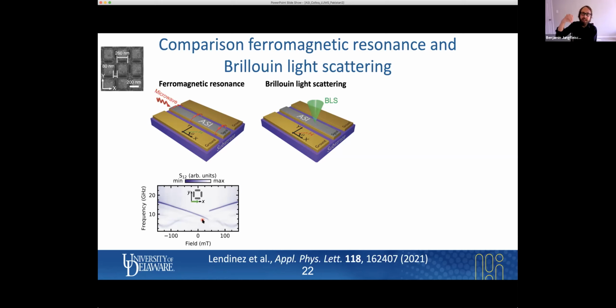So we shine our laser light, 532 nanometers, single mode continuous laser, on the same system, on the same artificial spin ice system as we studied by ferromagnetic resonance. Now we use a micro focus system, which means we collect the light over a large cone angle. So this means we also detect higher order modes that we are not able to see in ferromagnetic resonance. And the key difference, and I want to stress that, is we do not apply now any microwave drive. See, there's no microwave signal applied. We just measure the thermally excited spectrum.